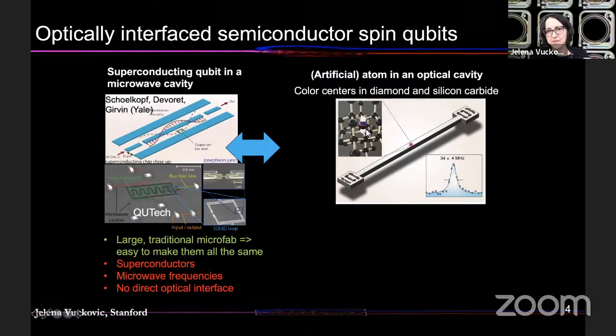So here, for example, you see an nitrogen atom inside of a diamond lattice, and you see two vacant carbon spots. Same configuration would hold for silicon vacancy in diamond, where you would have just a silicon impurity and then two vacant carbon spots, and a variety of other impurities that we work with. So we don't really need to trap this optically or magnetically, as opposed to atomic physics experiments where people work with neutral atoms or ions. Everything is already trapped inside of the crystalline structure. But of course, then there is a price you pay, and you have to worry about that interaction with the environment. It's not vacuum anymore, but that reduces complexity.